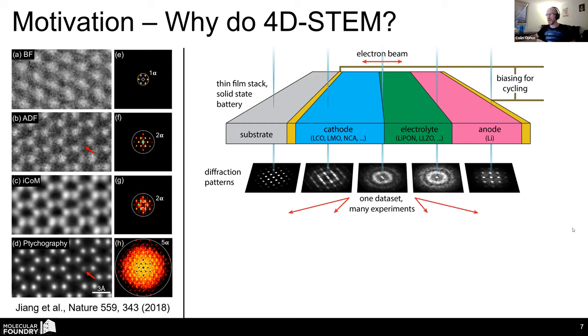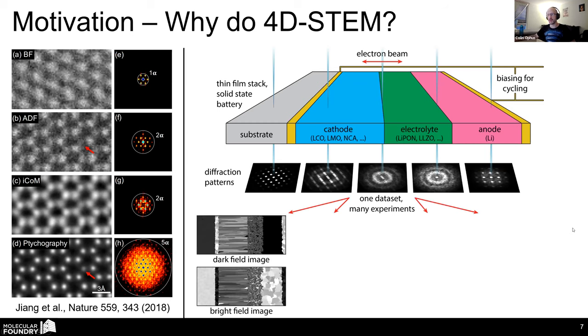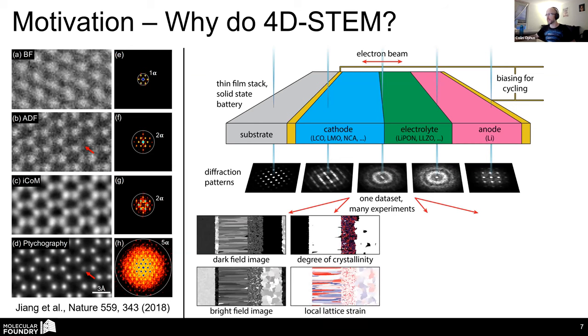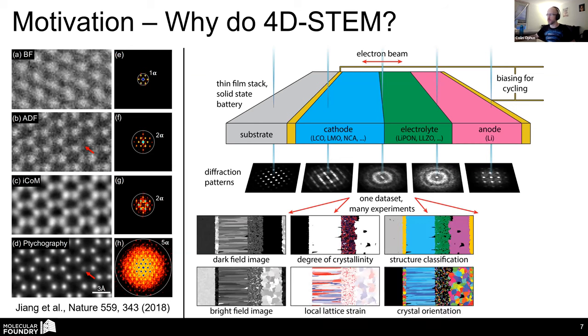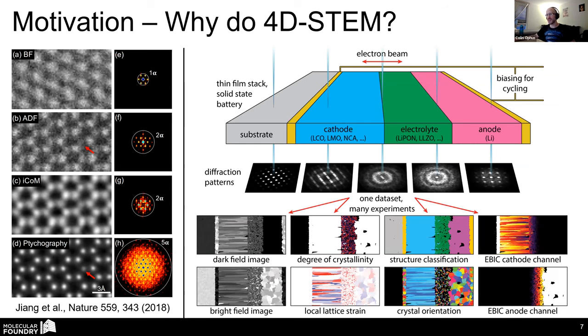And when we have this data set, we can then analyze it in many different ways. We could record the conventional dark field or bright field images, things like the phase mapping, degree of crystallinity, local deformation, structure classification or orientation, or even more exotic channels, for example, electron beam induced current shown here. So these are the two extreme length scales that I'll show in my talk today.